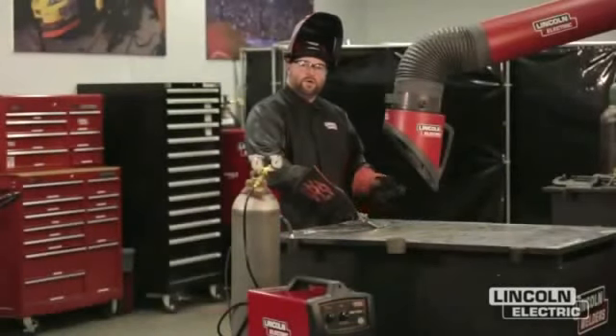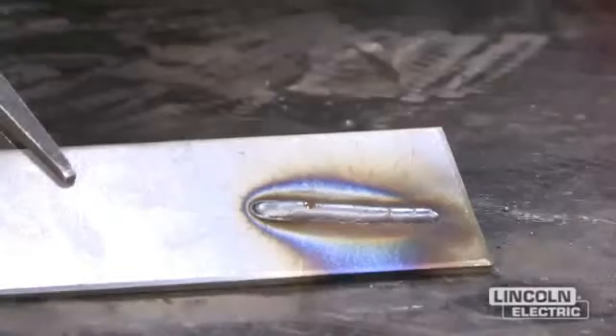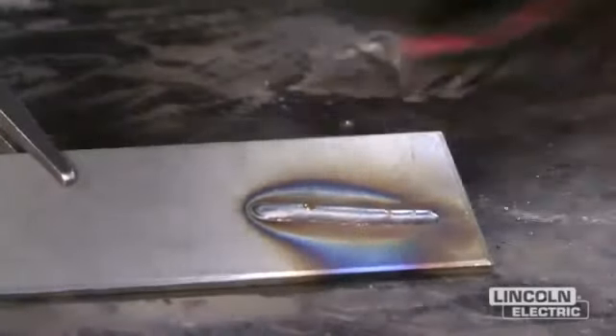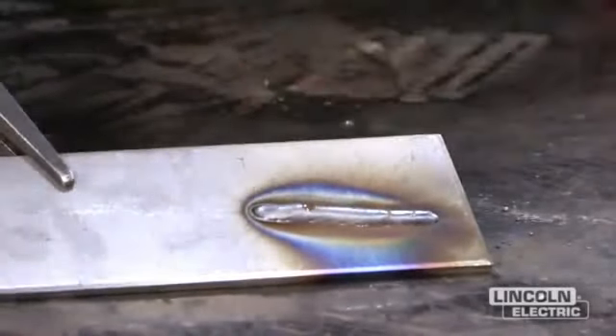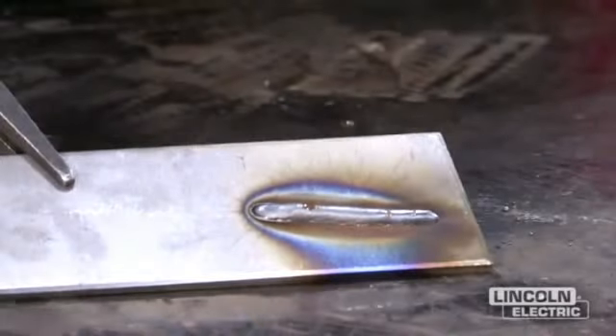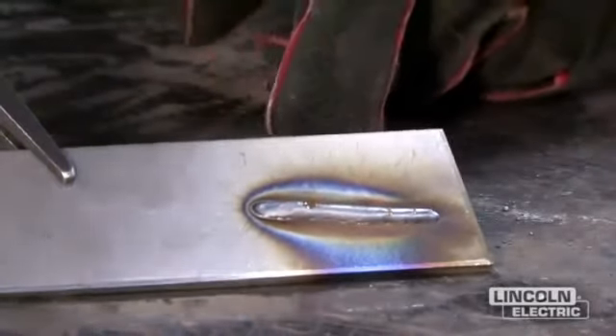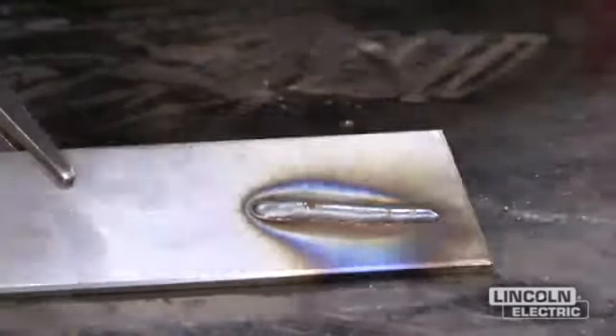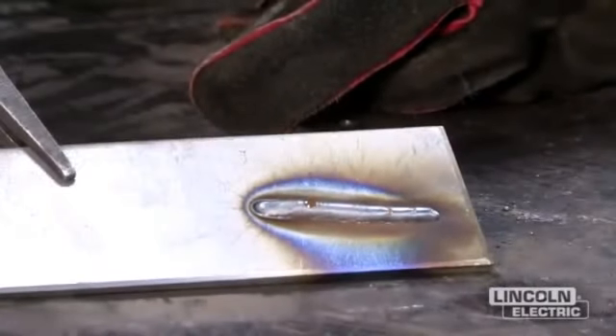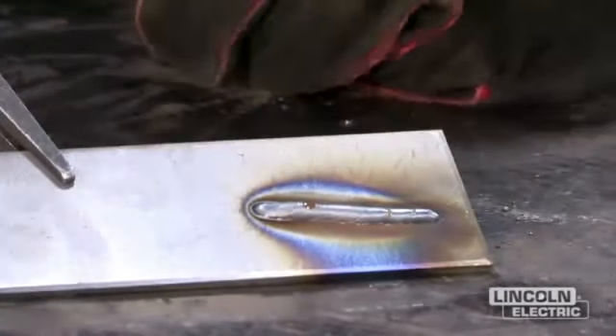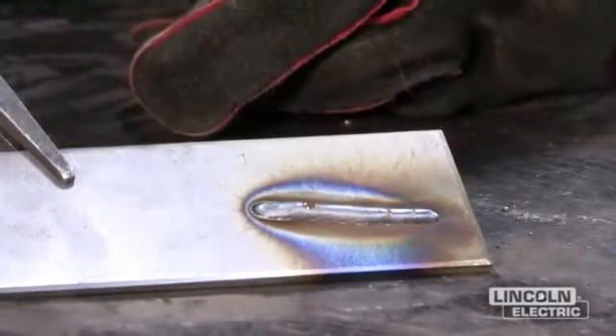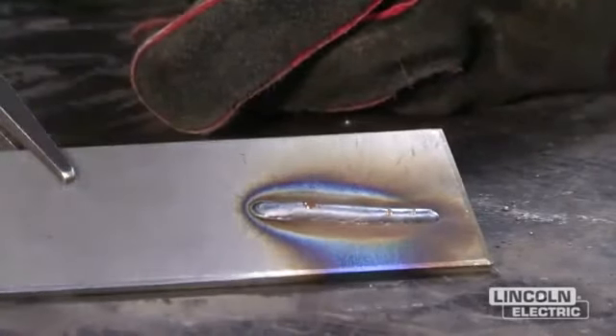So we just made a weld using a drag technique with the GMAW short arc. And you'll notice there's very little to no spatter, so our machine settings are correct, our wire feed speed, our voltage, even our travel speed. It's just that when you drag it, you'll notice that the weld is a lot more convex or humped up in the middle. But again, you will typically get more penetration on that type of weld.